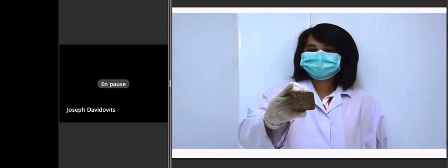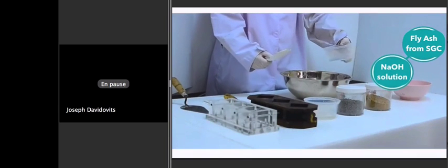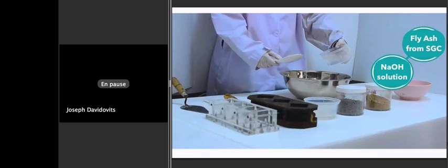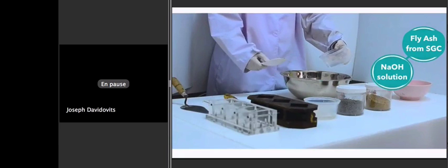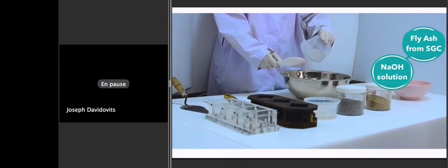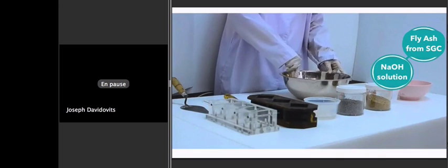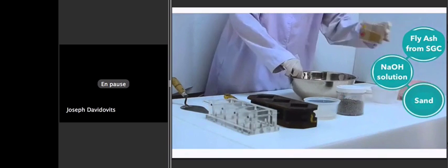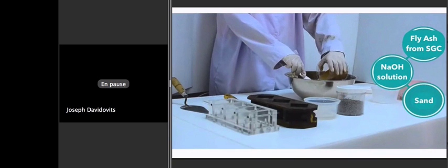So, what is wrong here? I explain. So we come backwards, start again. We have the fly ash first, then they add NaOH on the fly ash. So the fly ash will take a lot of the NaOH. Then they add the sand. That is, the sand is in contact with the NaOH and will take part of the NaOH on its surface. Fly ash reacts with NaOH and will be dissolved. Sand, absolutely not, but part of the NaOH will be in between the sand grains and will remain there.